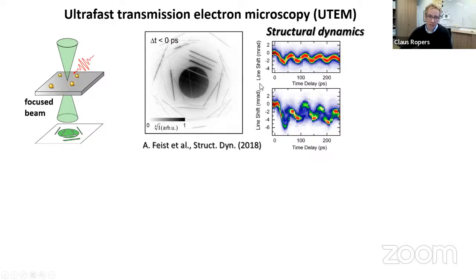So here, for example, it's just as a function of the optical pump, electron probe delay, the evolution of line positions and line shapes, which can then be used, as I said, to reconstruct the unit cell, and the strain evolution, the propagation of strain waves throughout the material.